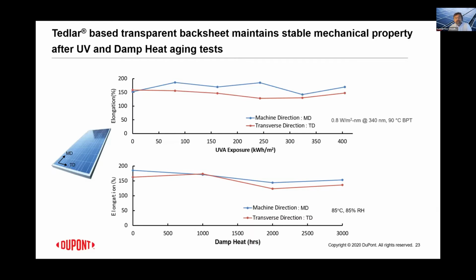What we see here is on top, with over 400 kilowatt hours of UV exposure, there's not really much change in these mechanical properties. On the bottom over here, we are showing damp heat exposures of 3,000 hours. Although I have to mention here that if I can go back to the field, we do not see a lot of correlation beyond 1,000 to 1,500 hours of damp heat exposure as an accelerated test. However, we do want to stress it well over the required IEC requirements. So we take it all the way out to the 3,000 hours. And again, we don't see any appreciable change in the mechanical properties. So it gives us the confidence in both the MD and the TD direction.